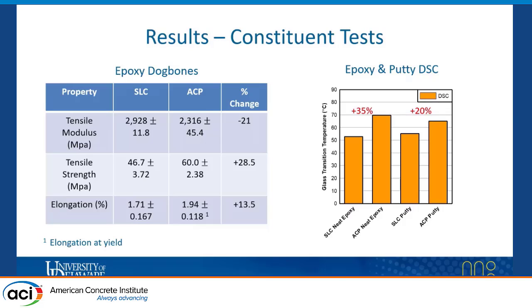As for the DSC results for epoxy and putty samples, it was found that after conditioning, the glass transition temperature of the epoxy increased by 35%, whereas for the putty samples, the glass transition temperature increased by 20% following conditioning. What these results are showing are the competing effects between moisture introduction and heat introduction to the epoxy. When epoxy is exposed to moisture, it plasticizes, it loses its stiffness, and it softens. However, when it's introduced to heat, it further cures the epoxy and promotes polymer cross-linking, or in other words, it polymerizes.